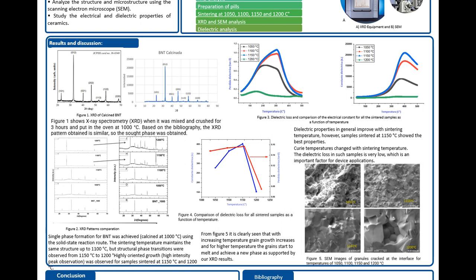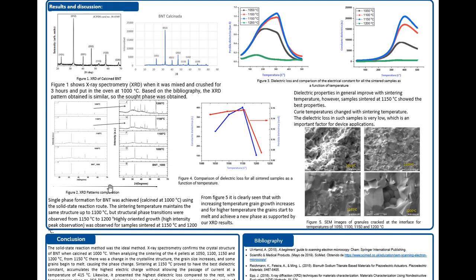So in the results and discussion, in figure number 1, we can see the X-ray spectrometry of the sample when it was mixed and crushed for 3 hours and put in the oven at 1000 degrees. Based on the bibliography, the XRD pattern obtained is similar, so the desired phase was obtained. Now we can see in figure number 2 how the single phase formation for BNT was achieved.